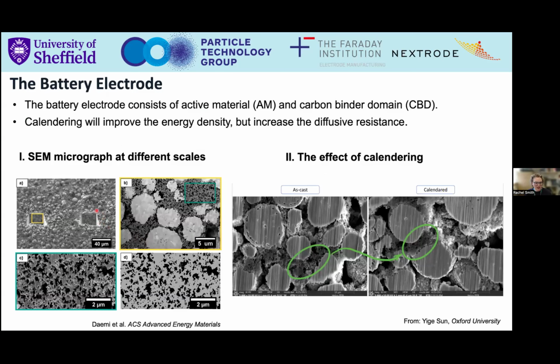Well, you can see here we've got electron micrographs at different scales of an electrode. These large particles here are NMC, nickel, manganese, cobalt particles. They're the active particles in the electrode. And here we have what we call the CBD phase, the carbon binder phase. And you can see it's a very porous structure. The structure of this phase is really important to the electrode performance, as I said.